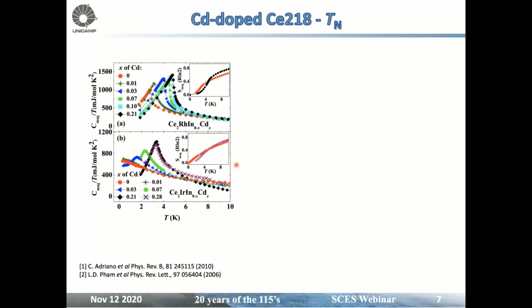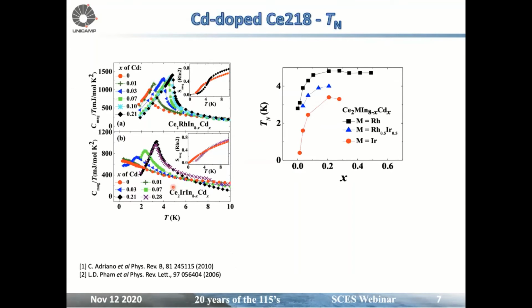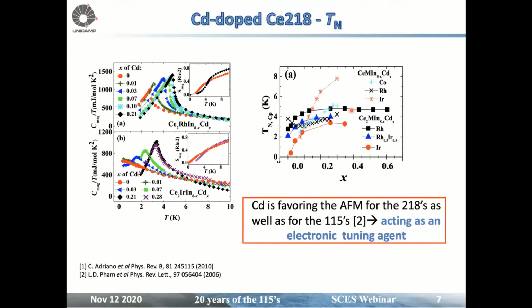So then I will show you cadmium doping in Ce218, what happened with TN. This is just to show that we doped the rhodium member and the iridium member, and if we put all the results together in a phase diagram of Néel temperature as a function of doping, including here rhodium half, iridium half, we see that cadmium is increasing the Néel temperature for 3 members of the series. So cadmium is favoring antiferromagnetism for the 218s as well as for the 115.